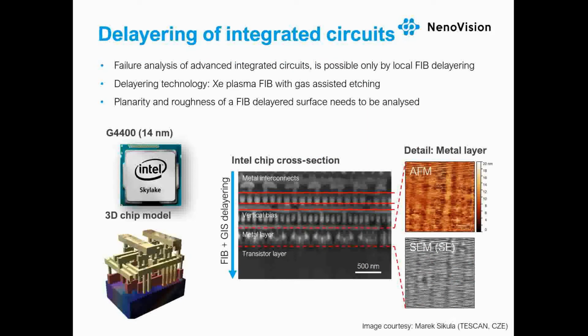The sample is a 14 nanometer technology node Intel processor composed of multi-layer structures that contain multi-gate transistors as key elements. A failure analysis process of such integrated circuits typically involves delayering and electrical nanoprobing. So far, delayering has been performed mainly by means of mechanical polishing. However, for future devices, mechanical polishing cannot be used due to micro and nanomechanical deformation and chemical interactions with the polishing suspension. Here, LiteScope was used for in-situ roughness analysis of individual layer interconnections for failure analysis and quality control purposes.